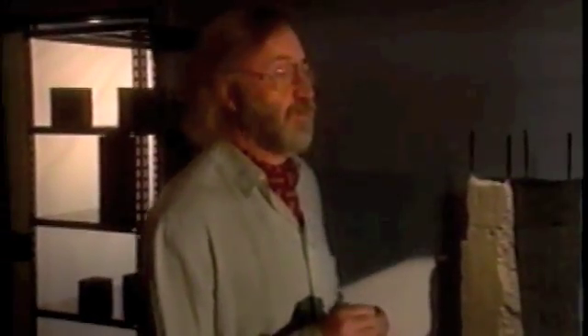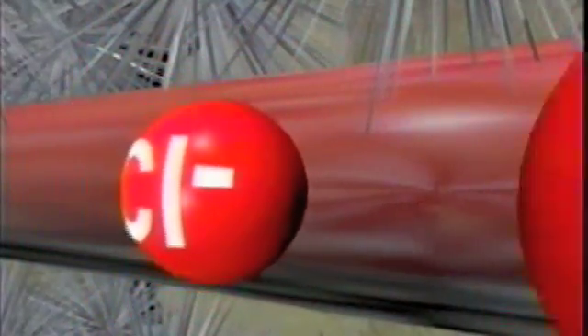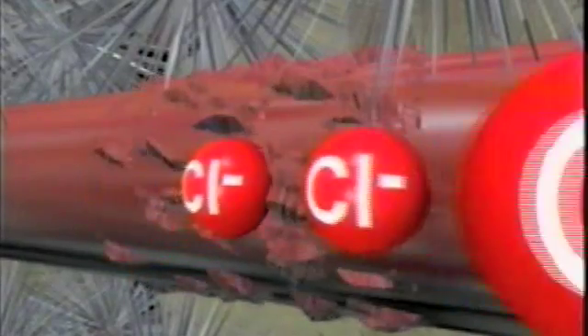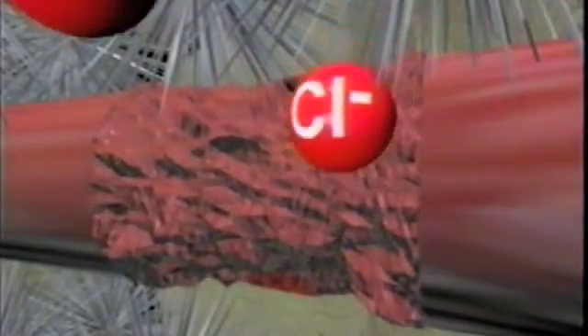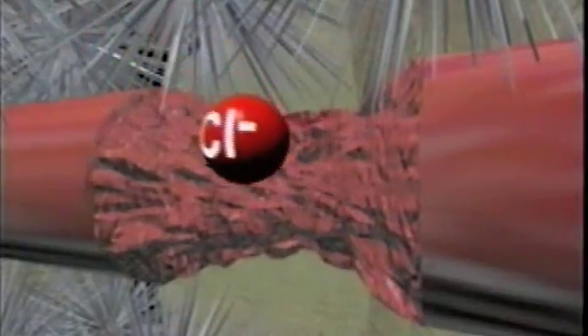The thin rust layer, which encloses and protects the steel bars, remains stable and compact as long as the amount of chloride remains below 0.2-0.3% by weight of cement. If, however, the percentage of chlorides increases, the rust layer becomes porous and no longer guarantees any protection to the steel reinforcing bars. The metal undergoes localized pitting corrosion, which dangerously reduces its diameter.